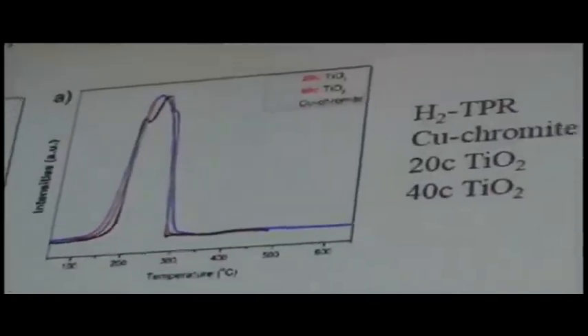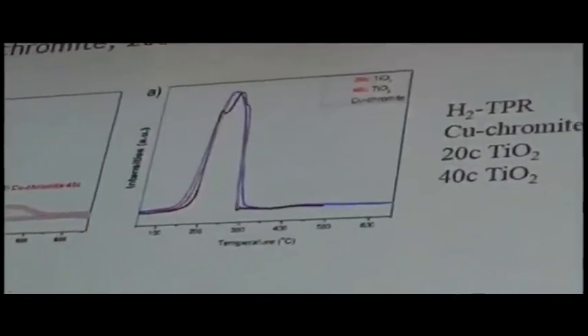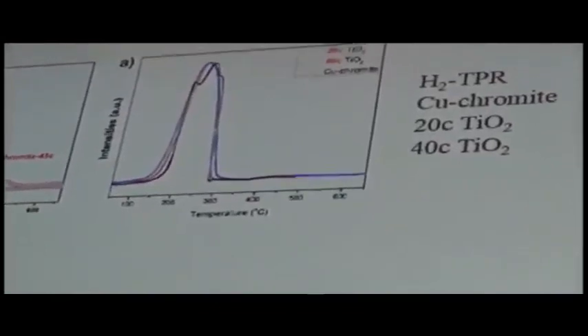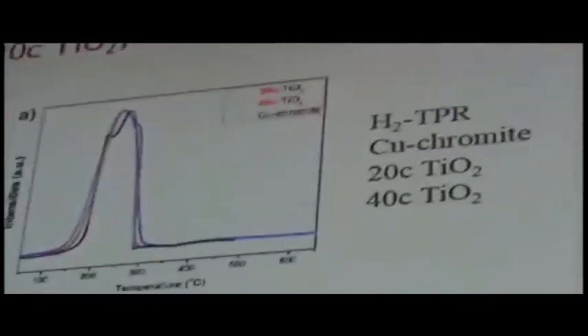So as you might expect, and I'm foreshadowing a little bit, the titanium is a far better overcoat for copper material. Now, I said that the problem with standard TPR is you really are not looking at the metal, so you're making some speculation about it. When we do the same experiment in the beamline, we're specifically looking just at the copper that we're interested in.